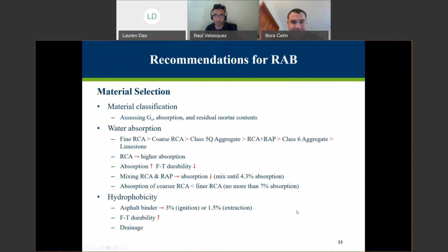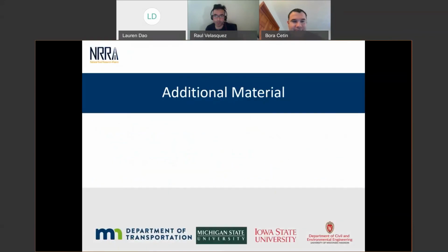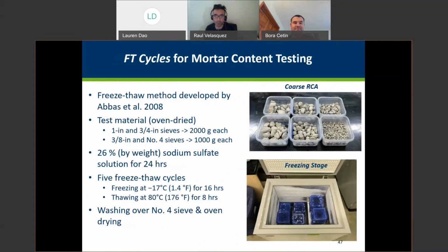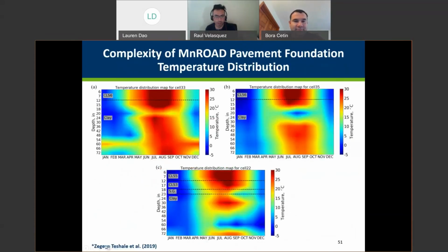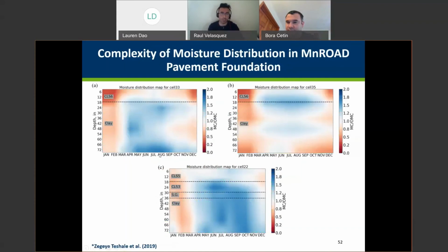Minnesota Research and the Office of Materials and Road Research are working quite a bit on that complex moisture distribution, and I want to show you some plots from some work done by Dr. Zegeye Teshale on that question. Due to the fact that we have precipitation plus a shallow water table. Here I'm showing just temperature distribution. Here I'm going to show moisture, how moisture changes along a typical cross section in MnROAD with the seasons. So we have a very complex boundary condition because we have the water table very shallow, about 5 feet. It varies between 3 to 5 feet depending upon where in MnROAD you're located. Because we have some subgrade that is sand, clay, that can hold way more water and can raise up the water table. And then that coupled with the precipitation gave us a kind of difficult distribution on profiles that are usually not homogeneous.